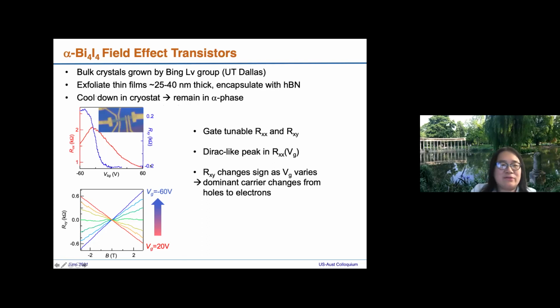What we have observed is basically a transistor behavior, which has not been seen before. We have a gate tunable longitudinal and Hall resistance. In the longitudinal resistance, which is the red one, we can see there's a Dirac-like peak as a function of gate voltage. The Hall resistance also changes sign close to where the peak is, but not exactly. The dominant carrier changes from holes to electrons, and here it just shows that the Hall resistance is linear in the magnetic field and changes sign as we tune the gate voltage.